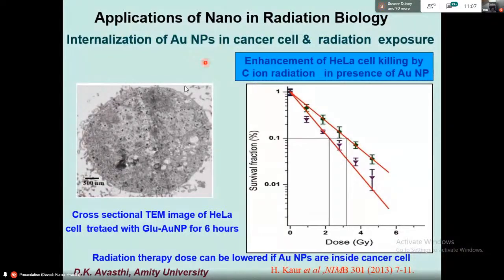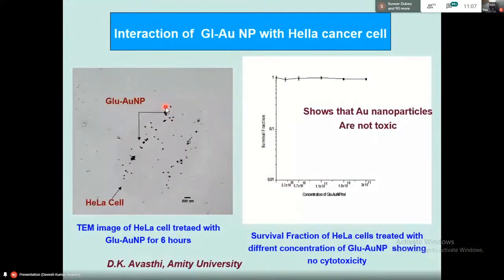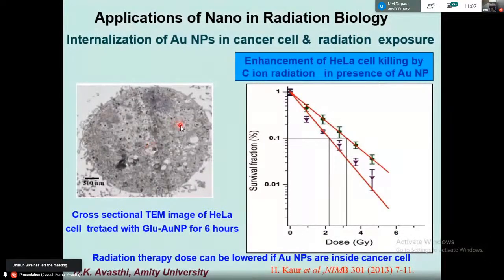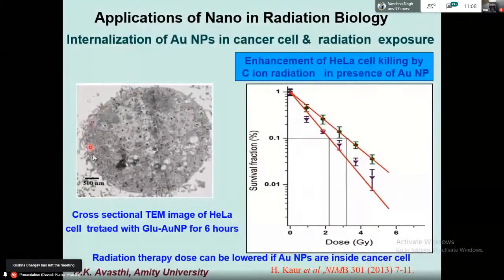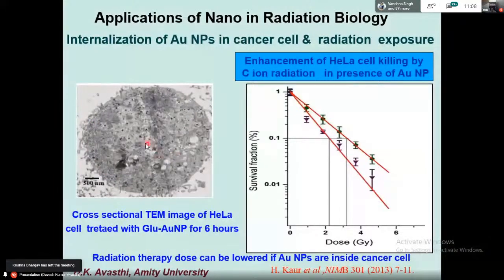Now, this is a picture again. In this picture, it is difficult to say whether these gold nanoparticles are inside the cell or on top of the cell. So we did a cross section of that. We cut the cell, this is called microtomy, and in the cross section you can see these black dots, which are the gold nanoparticles. This shows that gold nanoparticles have gone inside the cells.